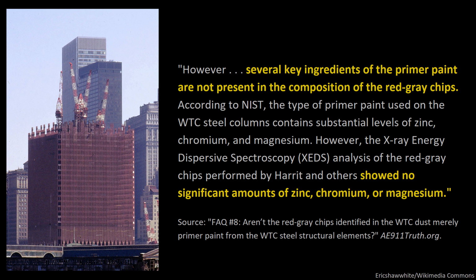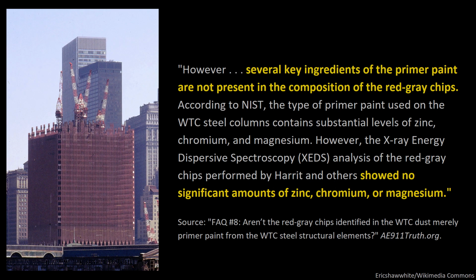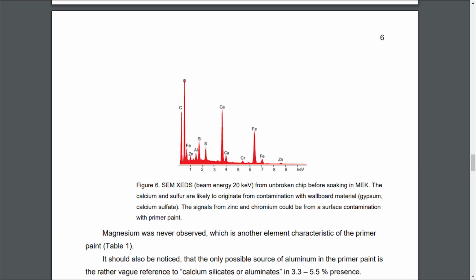However, the X-ray energy dispersive spectroscopy analysis of the red-gray chips, performed by Harrit and others, showed no significant amounts of zinc, chromium, or magnesium, end quotes. When you actually look at the chemical analysis they're referencing here, you find that they're simply misstating its results. All you have to do is look at the spectrum, and you find that the red side of the chips does contain the elements they say it doesn't.